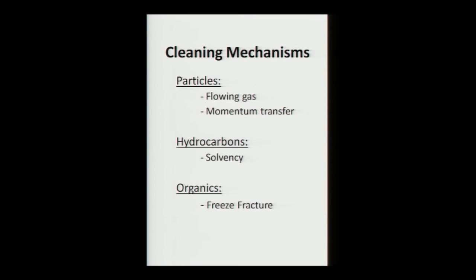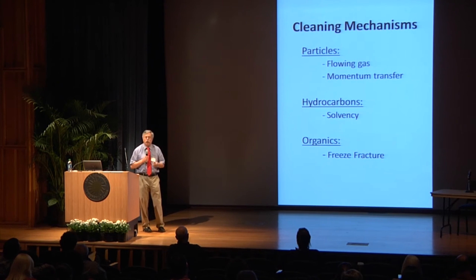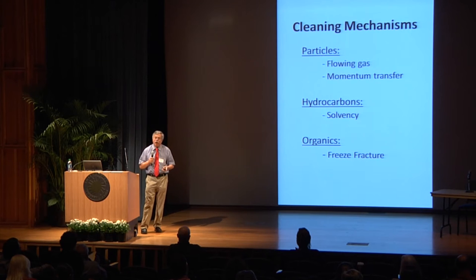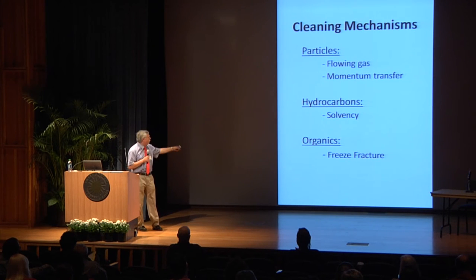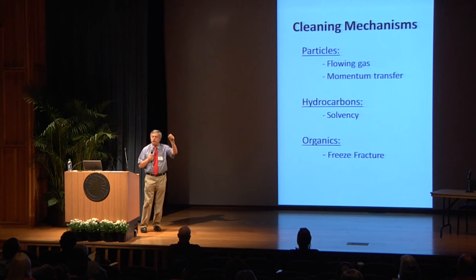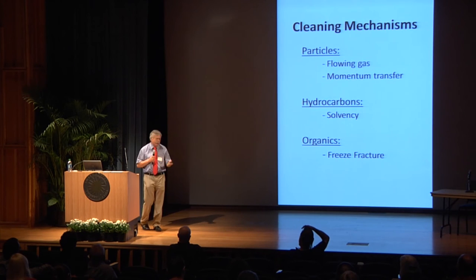Hydrocarbons, referring to the previous slide, it's solvency. Liquid CO2 is an excellent solvent. Unfortunately, it does not exist at atmospheric pressure. Organics, let's say like a silicone oil, a very thin layer of silicone oil, that's not soluble in liquid CO2. The cleaning mechanism is slower. It's called freeze fracture. We're freezing that layer and banging it off. So it's a slower process. If people use solvents and you clean, let's say, a glass surface, you get a stain in the corner, this process can remove that solvent stain.